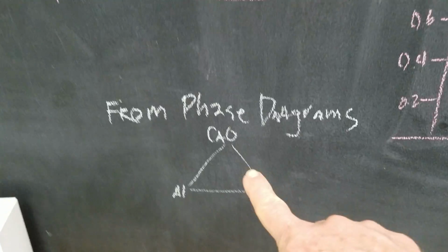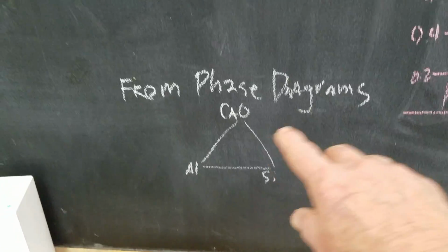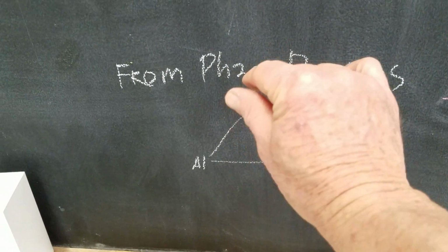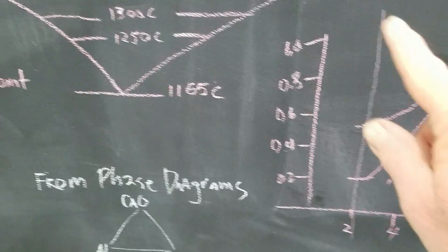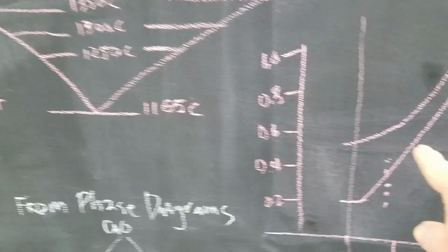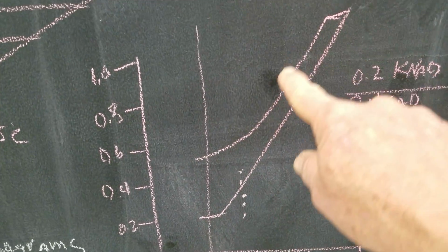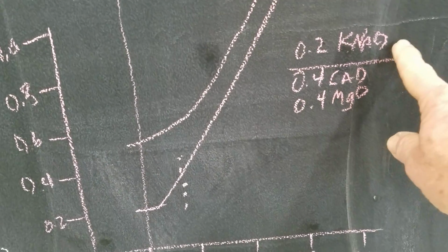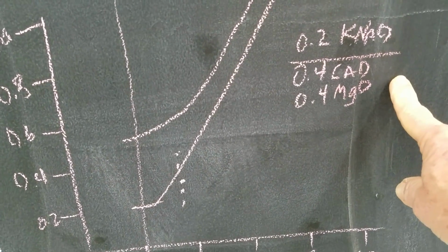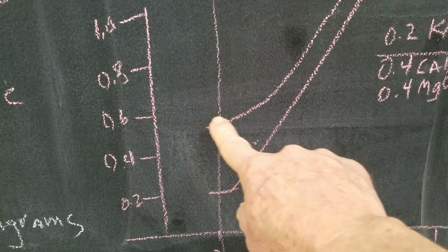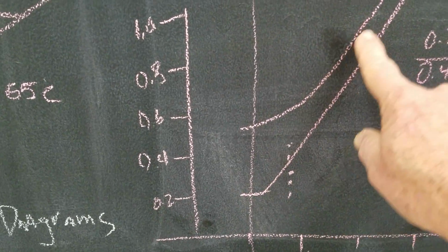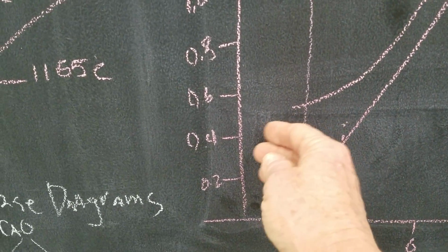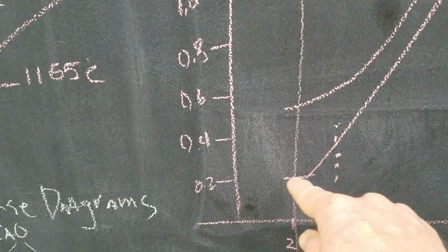Okay, so let me just show you this over here. So he'll take this phase diagram, he'll have a bunch of lines on there, and then he'll pick a certain area. That might be this area here, which I've plotted out for you. It's with this ratio of R2O, RO. And if I am within this line, that's my best melting. This means it doesn't make a good glaze, that's why it just stops.